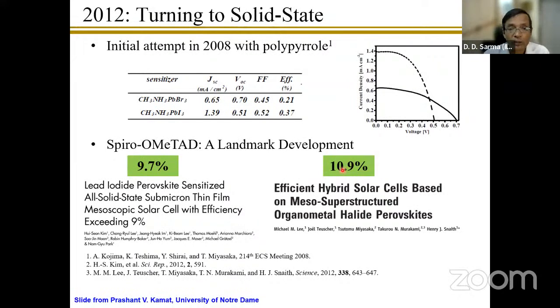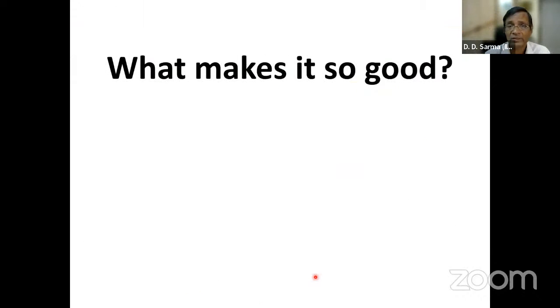When people saw that, and that's the 2012 papers that I'm talking about, once people saw that it can have 10% or more than 10% efficiency, everybody jumped into it. And then within this short time of less than 10 years, we have gone from 10% efficiency to more than 25% efficiency, close to 26% efficiency, which is a spectacular increase. Why is this material so good?